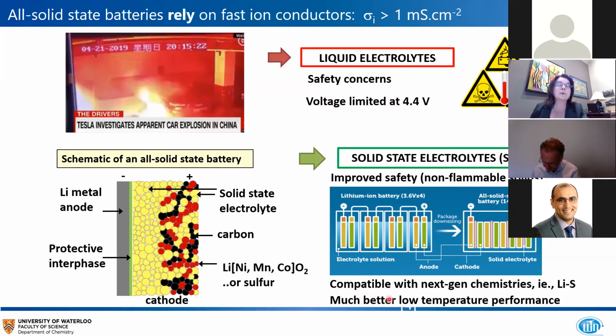And especially important to us here, they sustain much better low temperature performance because there's no viscosity of the solvent involved, but they also have better high temperature performance because, again, flammability of the electrolyte at high temperatures is not a concern. So this just shows a very simple diagram of such a solid state cell where we have a lithium anode, we have some protective interface like I was describing in the previous cells, and then the electrolyte is interwoven both as a separator and in the cathode. So we call this a catholyte because it has the electrolyte and the cathode within it.